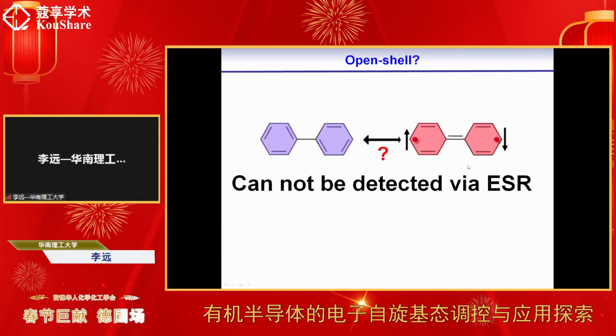However, we focused on the study for about 7 years, and we found that it is possible. It is totally possible. And for the wide band gap organic semiconductors, it can also be open shell. However, we cannot detect the radical via the ESR spectrum because the radical character is very, very low. But it exists, and we cannot detect it from the ESR spectrum.